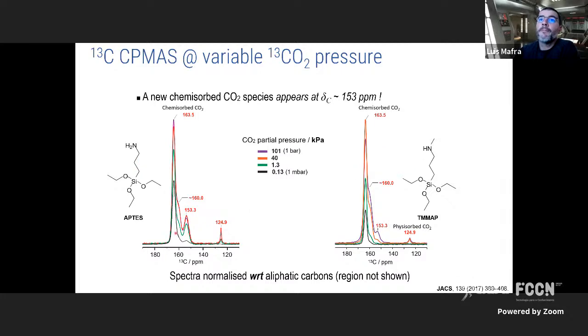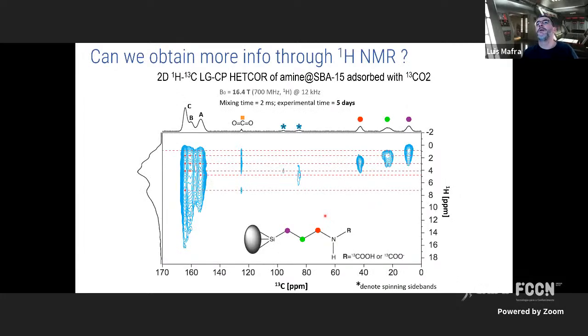You can see that at very low pressure, this intense peak is populated first, and then the other smaller environments start to populate, okay? And the kinetics of population also changes. I should say that the loading of amines is more or less the same, so we are in conditions that we can compare all this. And the spectra have been normalized. I will not go into the interesting details here, but I will just skip it for now.